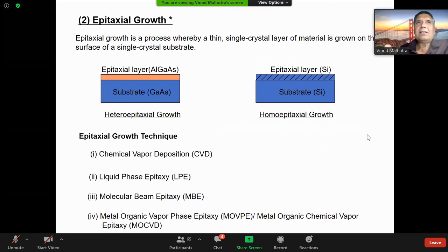Now, here's some interesting stuff. You'll find that the crystal that is made is essentially the substrate, which provides mechanical support. It's typically perhaps 400 to 500 micrometers thick. This is what the Czochralski method would give. By virtue of how it is made, it is not perfect. It has issues, but it nevertheless is a good crystal. The devices are made on top of it.